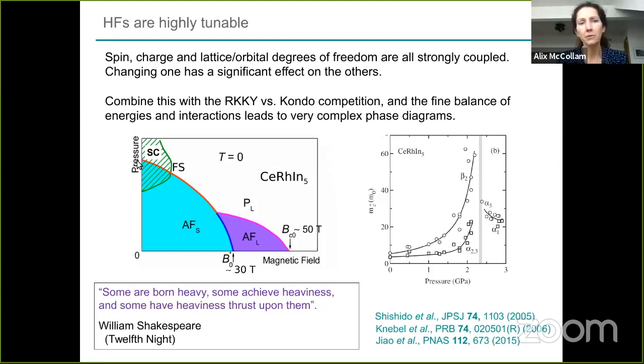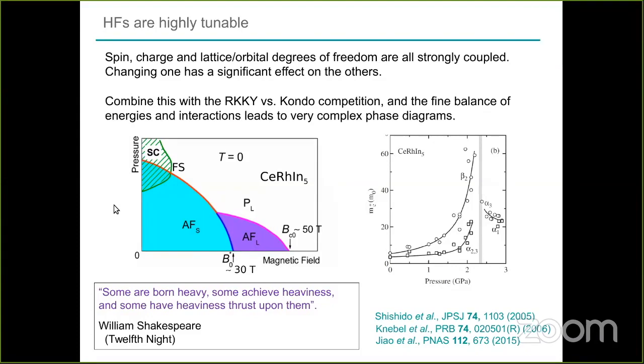So there are two quantum phase transitions here. With pressure, you can change the Coulomb interactions, amongst other things. With magnetic field, you can change the exchange, you're orienting the spins or trying to align the spins. So you're doing different things when you go in each of these directions, and indeed you get different physics. But also the things like the Fermi surface, which we can measure via the de Haas-van Alphen oscillations, for example. Very different things can happen in these two different regions, and that's what I will talk about in the rest of this talk.